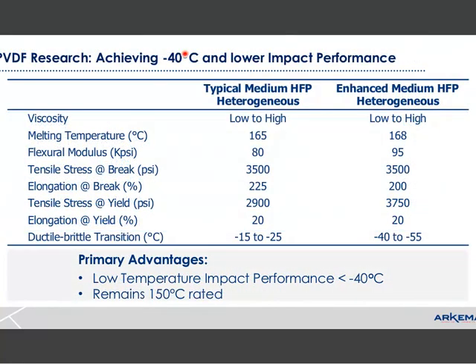Then for other products, we have products that go down to -40 degrees C, and in this case, comparing two heterogeneous products, one having our standard package and another one our enhanced package, we have very similar properties, but we were able to get the low temperature performance down to -40, -50 degrees, which is very significant.